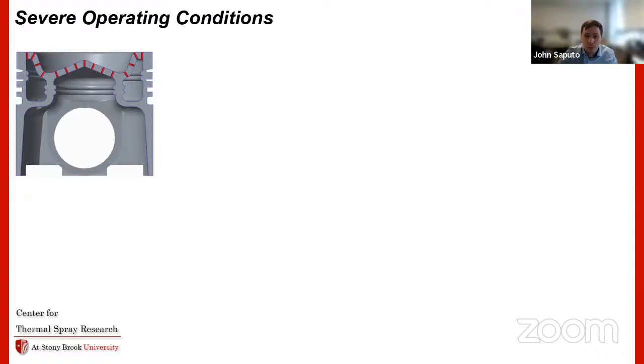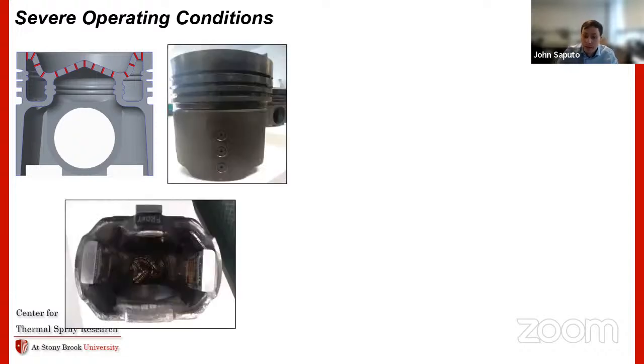So in these severe operating conditions, you really need some metrics inside of these systems outside of things like efficiency that we were looking at before. So the way you get that is, this is work that we did using telemetry pistons. Each one of those red lines that I'm showing on this sectional CAD model of a piston represents the location of a thermocouple implanted inside of a piston. So this is what this thing actually looks like, with some electronics screwed on to one edge there that transmit data. And then you can see at the bottom that silver line of thermocouple leads that are taped to go to this telemetry system.